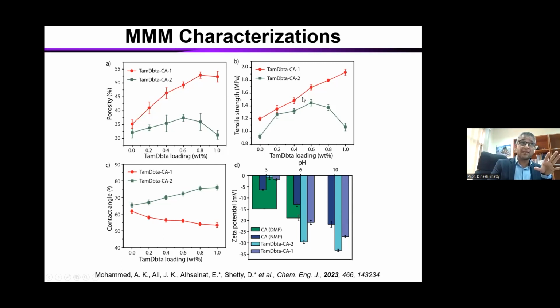In that tensile strength case also, when you have these pillars, you have a better tensile strength. In other cases, it's very difficult because in different regions there is aggregation, so obviously we can end up with variable tensile strength. Then for the contact angle measurement, when you see they are aggregated in regions, COF is hydrophobic in nature, so you end up getting a higher contact angle for the second membrane compared to the first membrane.